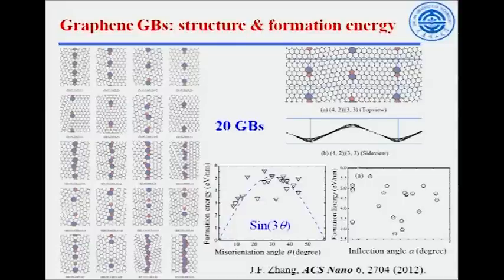Here is the inflection angle, so you can see the buckling here. Basically, the formation energy doesn't show much dependence on the inflection angle. Well, it has some relationship with the misorientation angle, which has already been proposed.